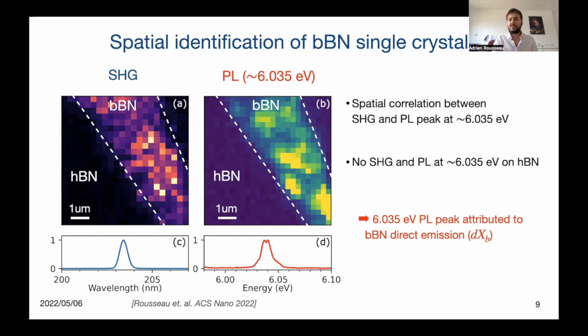Then we observe a spatial correlation between the second harmonic generation intensity map and the photoluminescence intensity map for the peak at 6.035 electron volt. And we observe no second harmonic generation and no photoluminescence intensity at 6.035 electron volt on the hexagonal boron nitride region. We then conclude that the 6.035 electron volt photoluminescence peak that we observe is attributed to the direct emission in Bernal boron nitride.